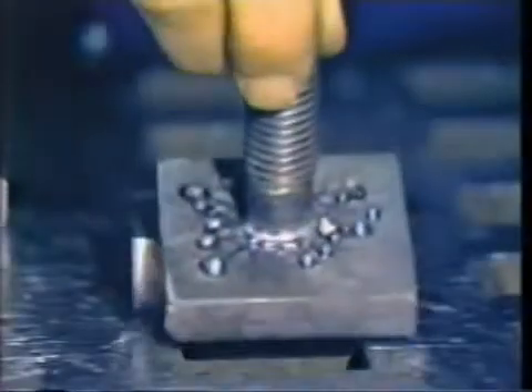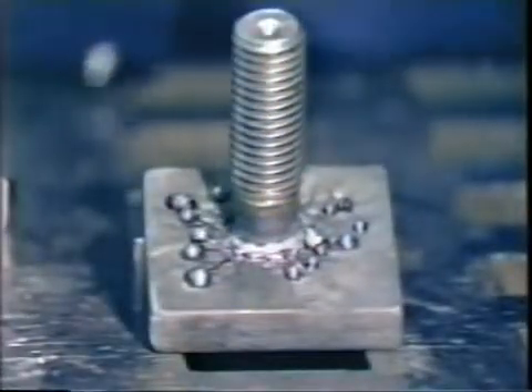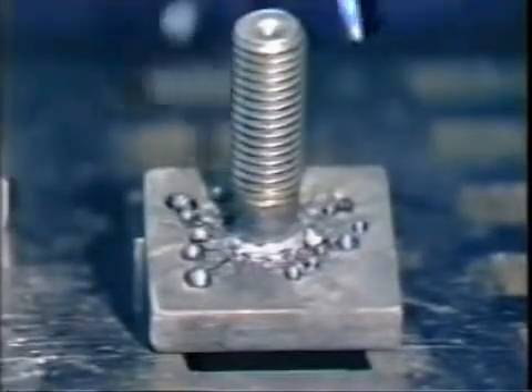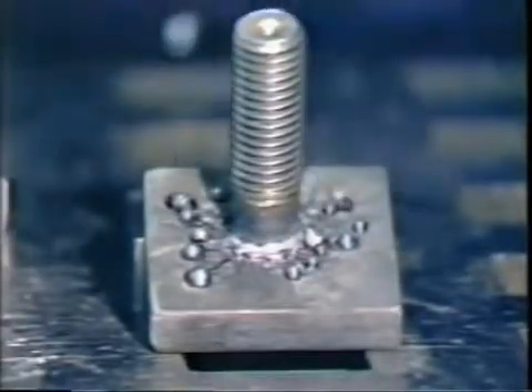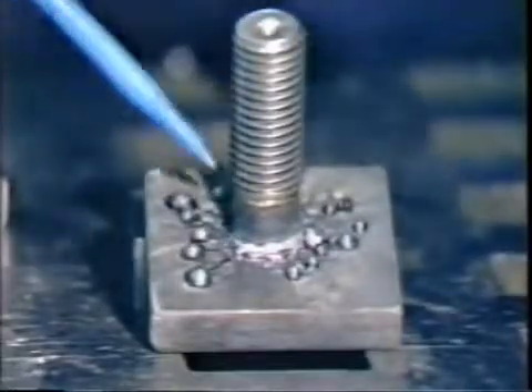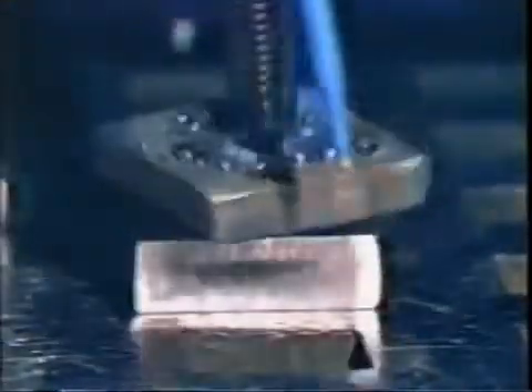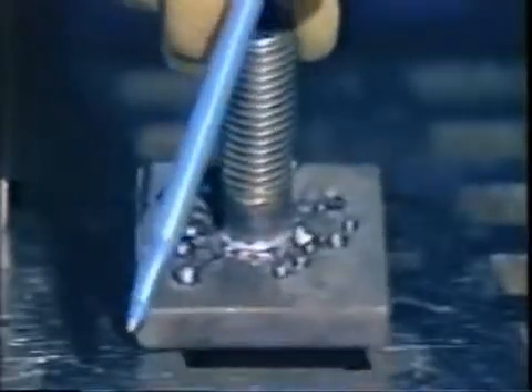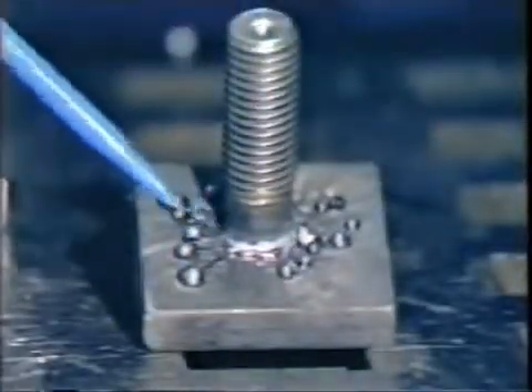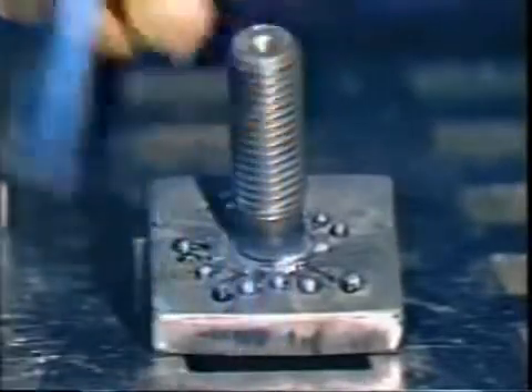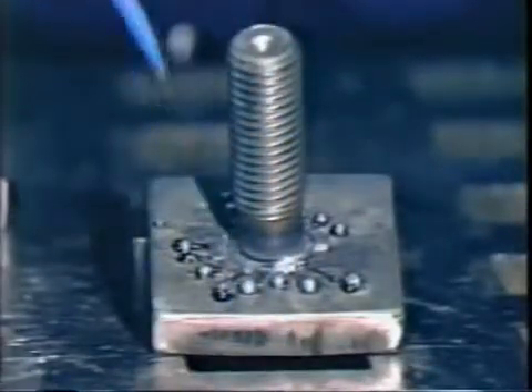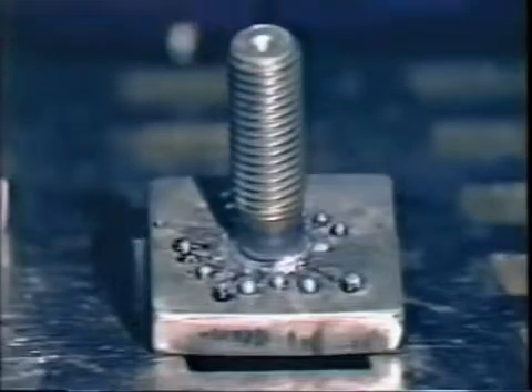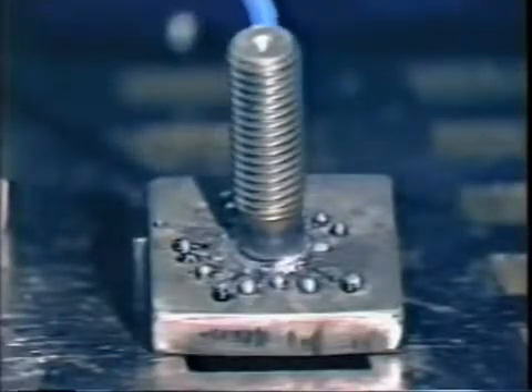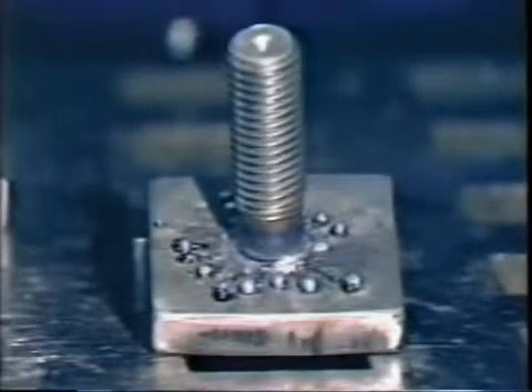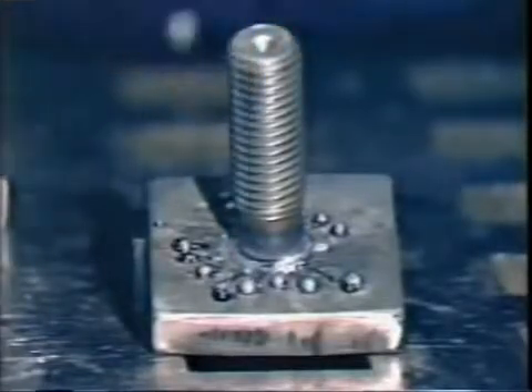The next weld is extremely hot. The weld berries are an indicator of too much heat. You get undercutting in here. The back side of this one is severely undercut. You have a gouging into the base material, a washing away of the material. The amperage setting or possibly the time were way too high on this one.